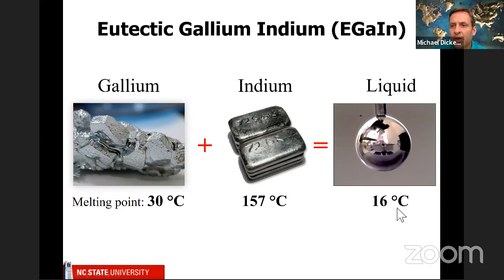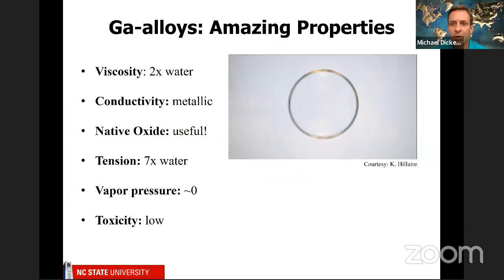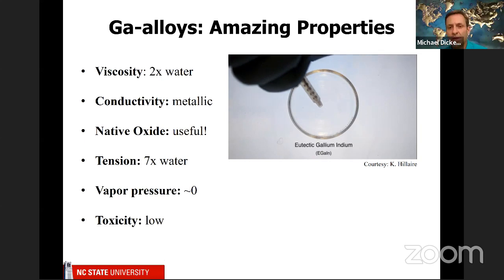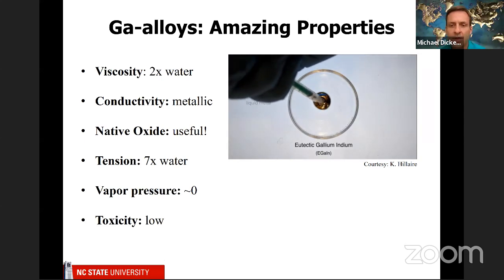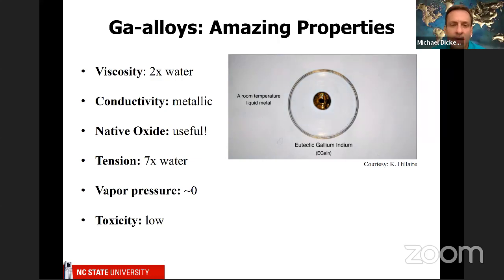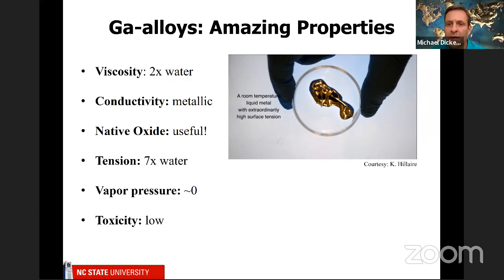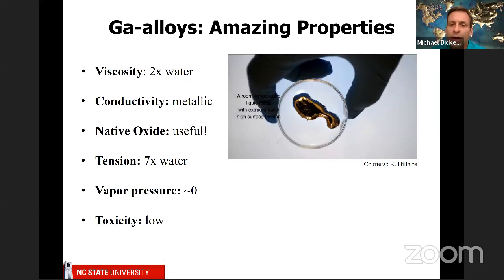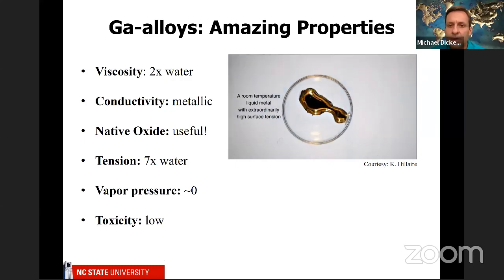Now, I'd like to tell you a little bit about what makes this material extreme, and it has several accolades that make it the best in category, and I can show you this through a video. So this is a syringe full of this liquid metal, and you can extrude it from the syringe no problem because it's got low viscosity. In fact, its bulk viscosity is like water. It does have metallic conductivity. It's about an order of magnitude less conductive than copper. And you see that if you slosh it around, it spreads and it holds its shape due to a very thin oxide layer that forms on the metal.